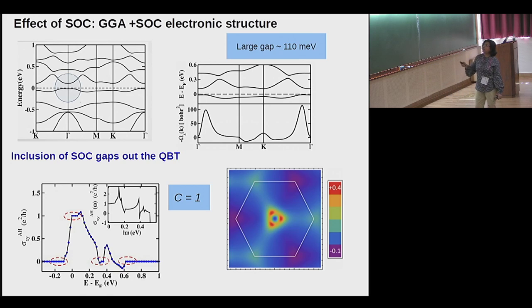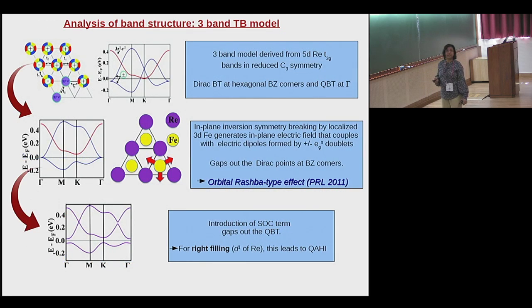And if you calculate the Berry curvature, it has a very highly peaked value close to the gamma point. If you integrate this Berry curvature over the entire 2D Brillouin zone and sum over all the occupied bands, what you get has a highly quantized structure, with its value at the Fermi level being 1. So we managed to get a Chern number 1 topological anomalous insulator. And you can write a simple tight-binding model and understand what is going on.